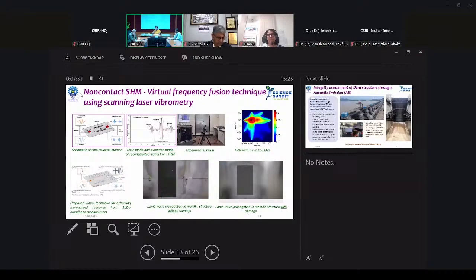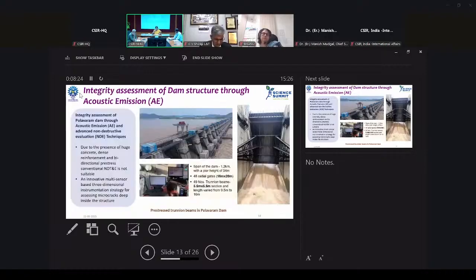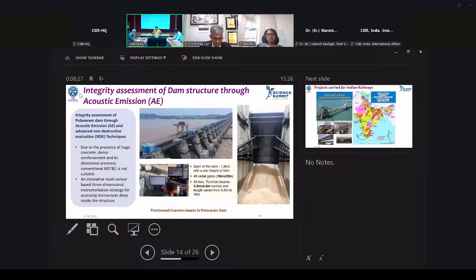So here, if you have some thin wall structures, like a pipeline, or a shell structure, we have used a non-contact SHM technique using a scanning laser vibrometer, by which you can pinpoint the exact damage. We are using the Lamb wave, which has a velocity of 5 kilometers per second, so that you can actually monitor long range pipelines, even intercontinental pipelines. Those techniques were developed in the laboratory.